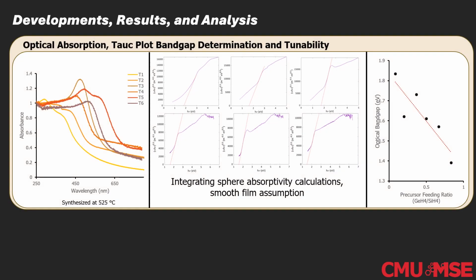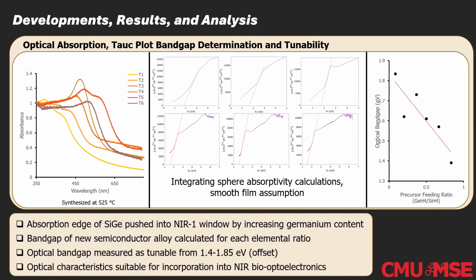Once the target synthesis conditions were identified, the optical properties of the material were examined. Through 6 precursor ratios with increasing germanium content, we saw the red shifting of the silicon germanium absorption band to nearly 750 nanometers, while reaching the near-infrared 1 window. From these measurements, we also extracted the absorptivity of the films to perform Tauc plot band gap calculations, which showed a trend of decreasing band gap with increasing germanium content, albeit shifted due to calculation assumptions. Through these successive rounds of synthesis and characterization, we've shown that silicon germanium has potential for near-infrared neural stimulation with its high absorption and suitable morphology.